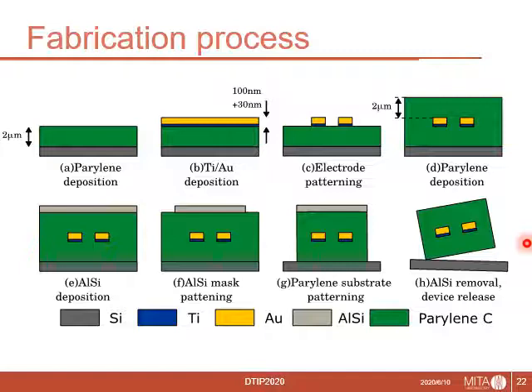By sandwiching electrodes with Parylene C, self-peel-off of electrodes was prevented while wrapping our device to a unit robot shell. Then, 100 nanometer thick aluminum silicon alloy was sputtered and etched to form the outline of the device. Because Parylene C has chemical inertness, it was etched by O2 plasma etching with aluminum silicon mask. After patterning of Parylene, the device was peeled from silicon substrate by surface tension of aluminum etchant while an aluminum silicon mask removal. When the device did not come off, an ultrasonic cleaner was utilized.